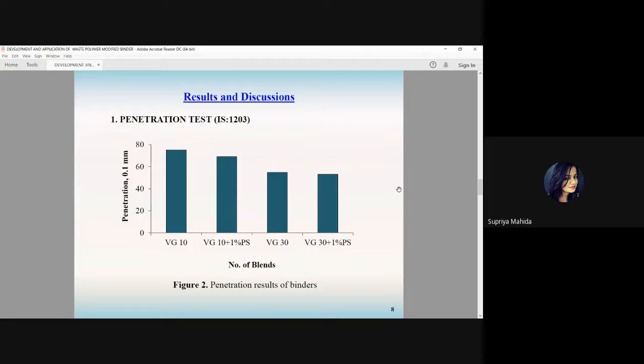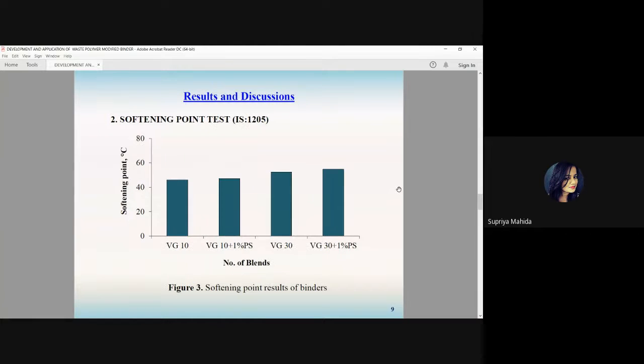So when we add 1% of thermocol in the conventional bitumen, either VG10 or VG30, the penetration value decreases. That means the bitumen becomes harder after adding the thermocol waste. So that gives the proper hardening of the bitumen that will affect the strength. And the penetration test is performed with the help of a penetrometer. Then we test the softening point.